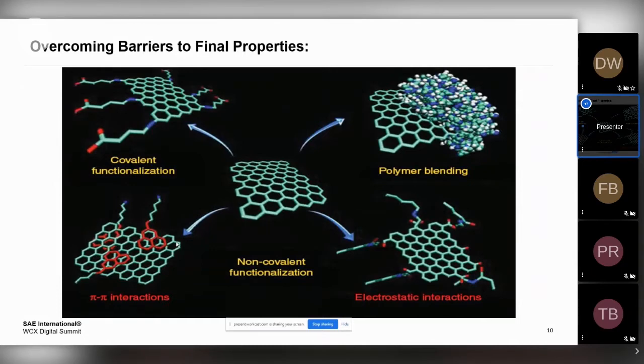Overcoming barriers, the final properties. One of the several routes that we can take is covalent functionalization. On the very edges of the graphene, it's possible, through the presence of the sp2 hybridization, to perform a nucleophilic or other type of chemical attack on that edge area, and then you can bond the chemistries to the substrate. Another approach is to blend it into polymers and compound it in such a way that you're working with polymers that have an affinity for it.